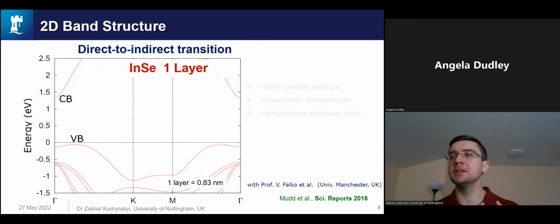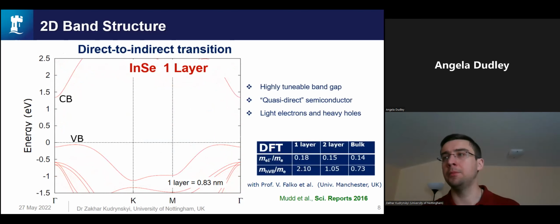The conduction and valence bands are at gamma point, but as we thin the layer, the valence band shifts. So as we go to a thinner layer, you see the band gap increases, but also the valence band changes significantly. The gap opens more as we decrease the number of layers. And finally, the valence band is significantly changed for a single layer. The valence band shifts away from gamma point and the crystal becomes indirect.